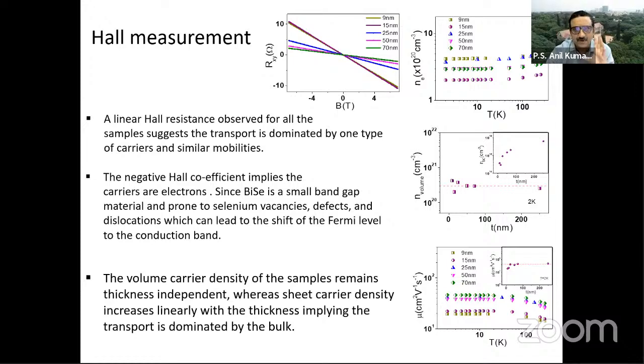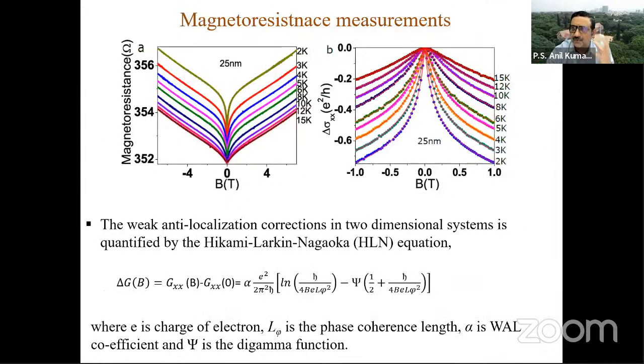But that's not the important aspect here. I just wanted to prove that this also shows exactly the same electrical property as that of a bulk crystal. If you look at the 25 nanometer film here, again, you can fit it with this weak anti-localization HLN equation. This is the experimental data and the fit to this equation. From this, we extract parameters like L_phi and alpha for this system.